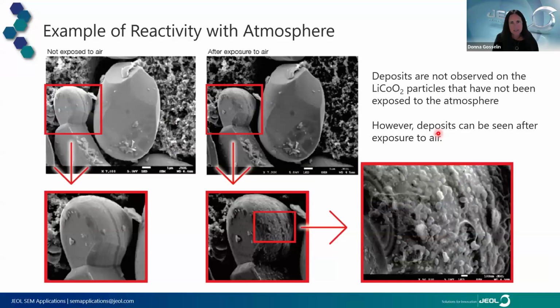But quickly, this is an example of why air isolation transfer can be important with some systems. So these are images of lithium cobalt oxide particles. On the right-hand side, you can see this has been exposed to air, and on the left, this has not been exposed to air. With an air exposed sample, even just briefly, you can see deposits here. There's an expanded view right here on the surface of the material formed because of rapid oxidation. And so this oxidation will mask the true surface structure. So you're not really seeing the true nature of what your particles look like.